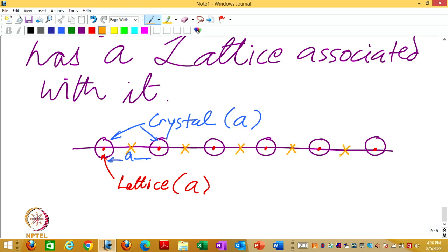If I select the midpoint of atoms, then that choice of origin which I told you, I have selected a different origin, but have I got a different lattice? In a way, yes, a different lattice because it is shifted, but actually we will consider both of them an identical lattice, only shifted. Both the dots and the crosses are periodic sets of points with the same periodicity. So, they are representing the same lattice and both are connected to my original crystal. Both are lattices of the pattern, the difference is only the choice of origin.